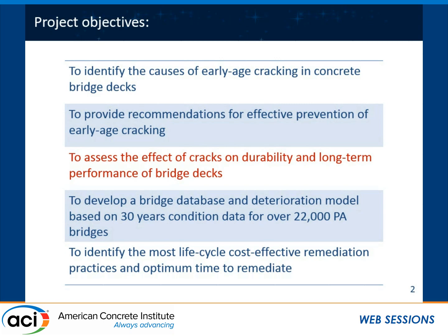And then take that a step further to figure out what is the effect of cracks on durability and long-term performance of bridge decks. Through some of the work that we've done, we address this third problem to some extent, but we also put in data collection procedures for PennDOT that now they are actively monitoring crack development over the bridges in their biannual inspection, so they can look at how a certain extent of cracking would result in a speed of deterioration in bridges.